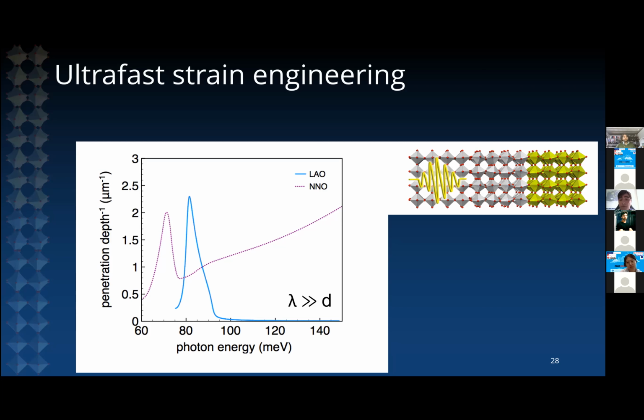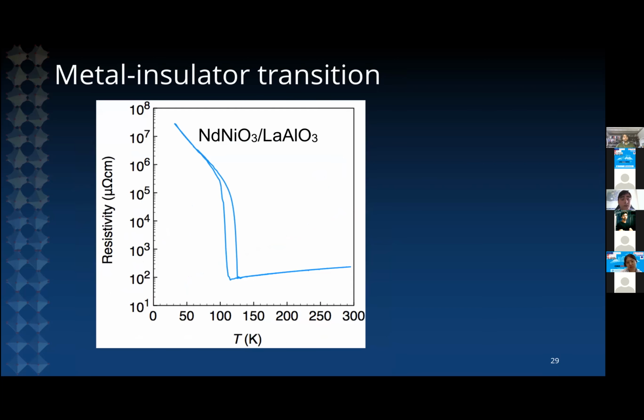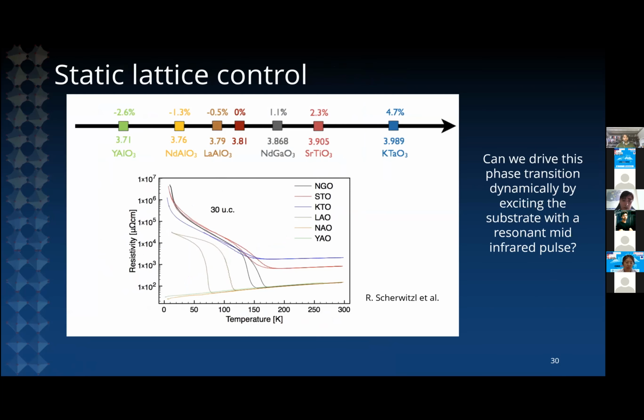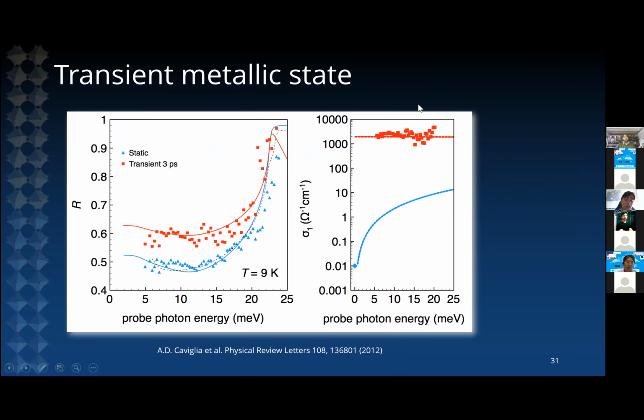So now we can understand this classical dynamics. Let's apply it to a thin film. So we have epitaxial thin films on top of this crystal, lanthanum aluminate. So we consider neodymium nickelate that has a transition from a metallic state to an antiferromagnetic insulating state. And when you grow the neodymium nickelate on different substrates, the epitaxial strain can tune the transition temperature to a very wide extent. And in this work, we have shown that this type of insulator to metal transition can also be driven dynamically by exciting the substrate material, as I just showed.